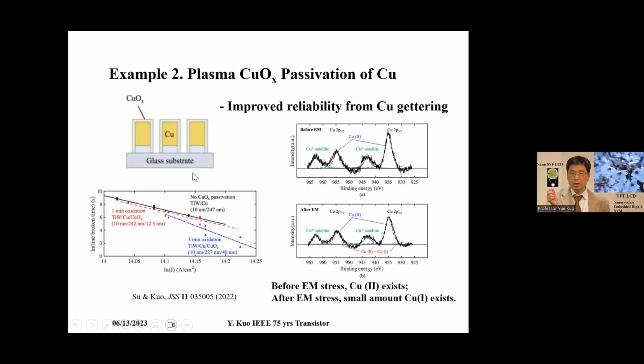But the advantage is under electromigration conditions, because under high current density electromigration, copper will diffuse out. And in the conventional case, copper will diffuse into the adjacent dielectric and cause reliability problems. However, if we have a thin oxide formed by plasma, then during electromigration, copper diffusing through the thin oxide is gettered because copper forms Cu2O oxide. So in that case, it's gettered there before it can diffuse into the dielectric. So it helps the interlayer dielectric.